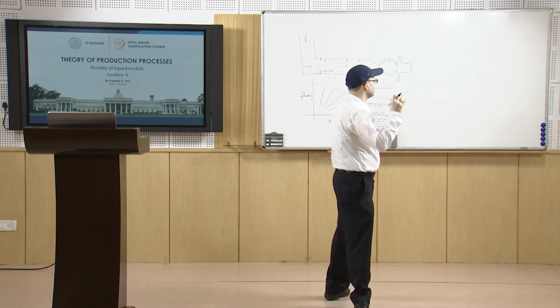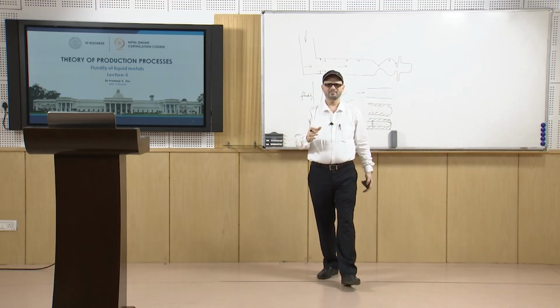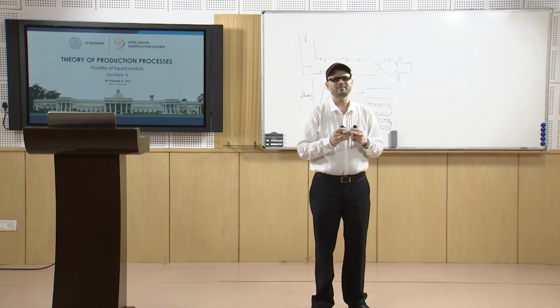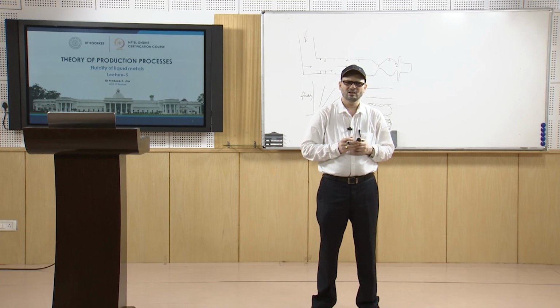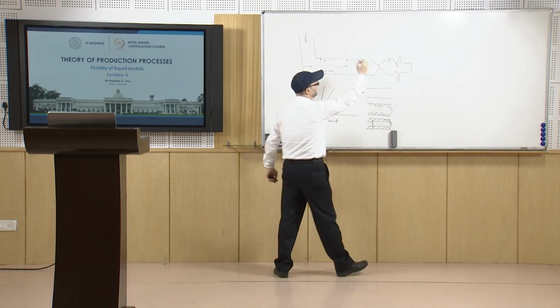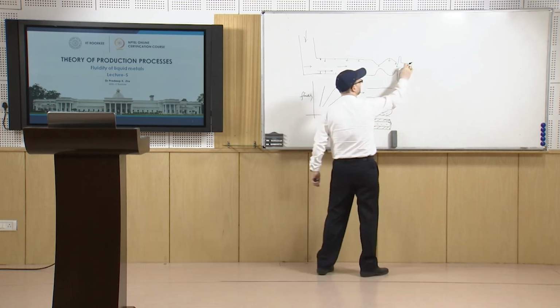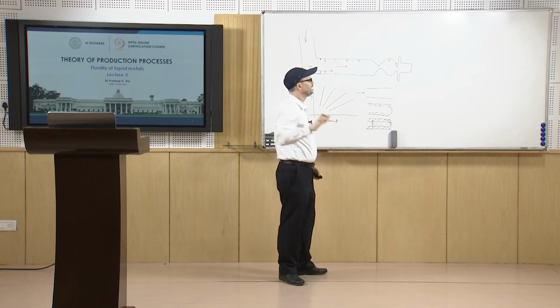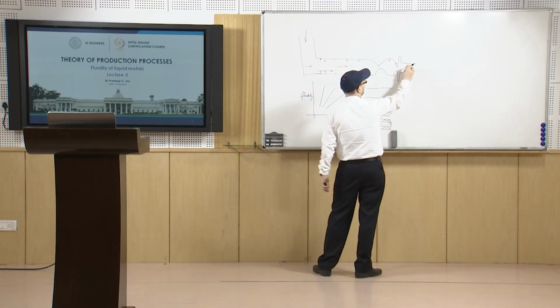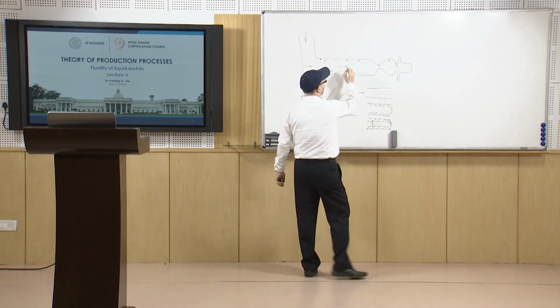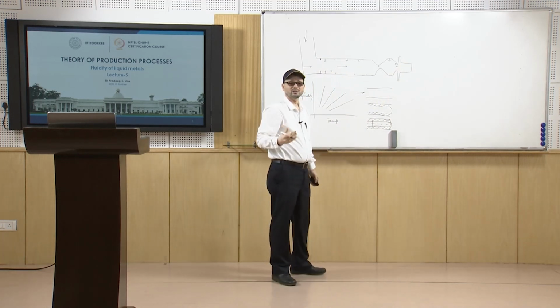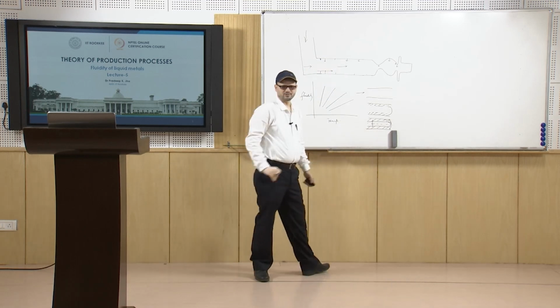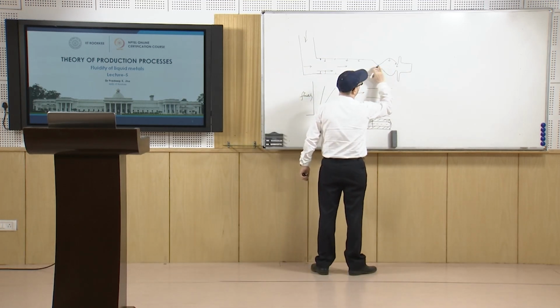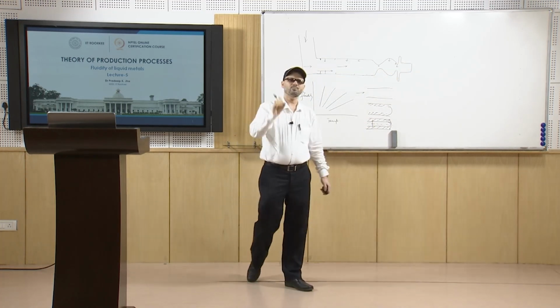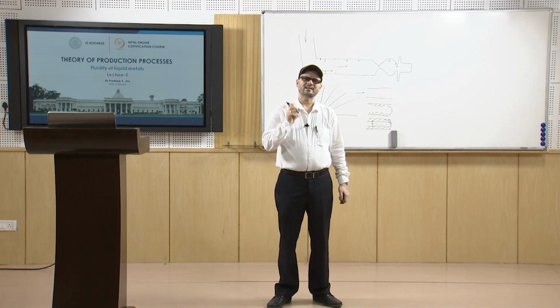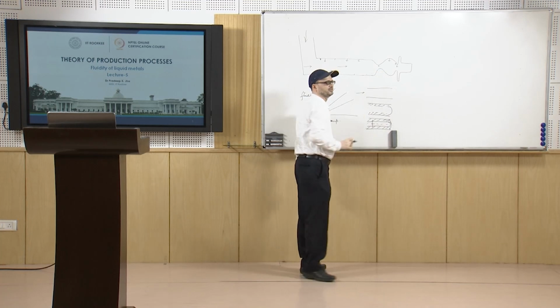So, if the molding material's permeability is not adequate, then many a times the liquid metal which is moving gets the pressure from the gases. What will happen if the liquid metal is moving and there is gas trapped here, and the gas is not able to go out? Fluidity is anyway there, but if the gases are trapped at the end and are not able to escape, then this gas will have a back pressure, and this will ensure that this liquid metal will not be able to reach the end point. So, that is another factor which affects the fluidity.